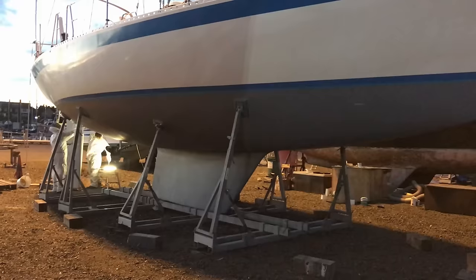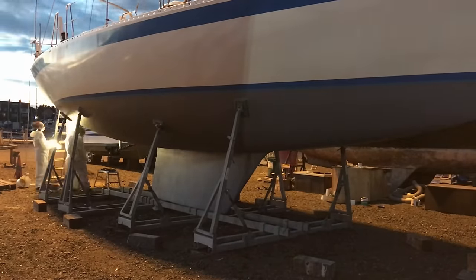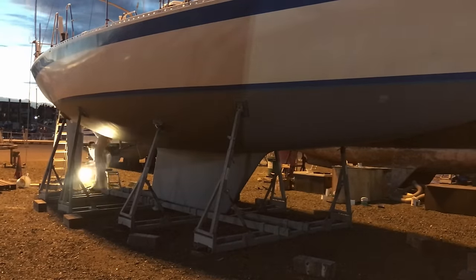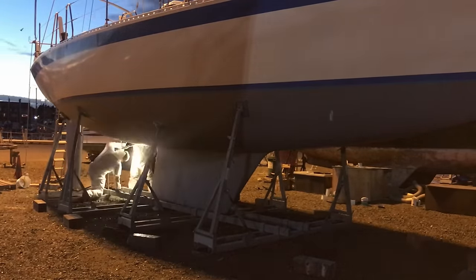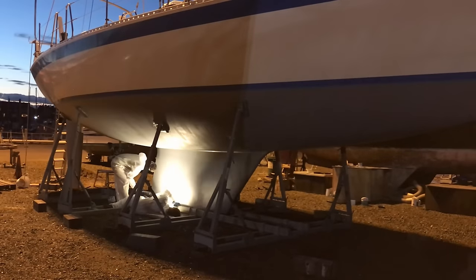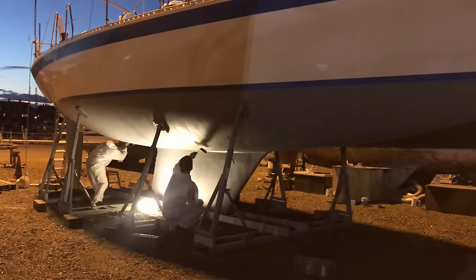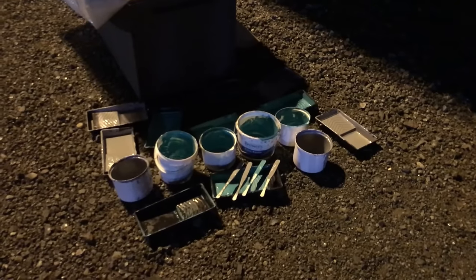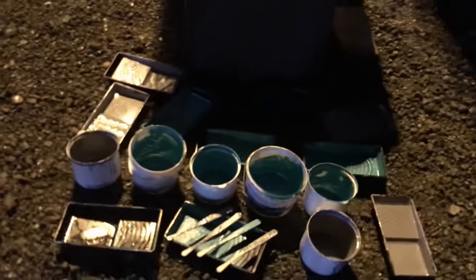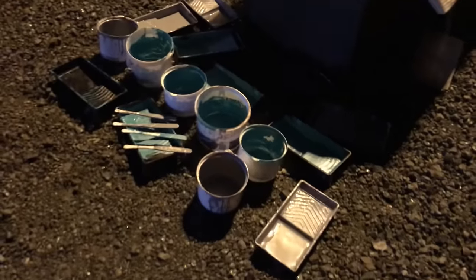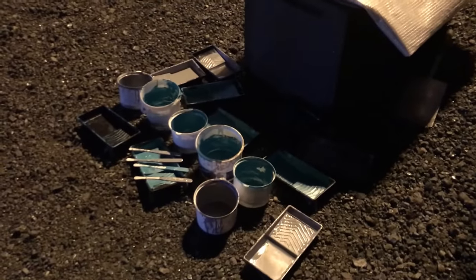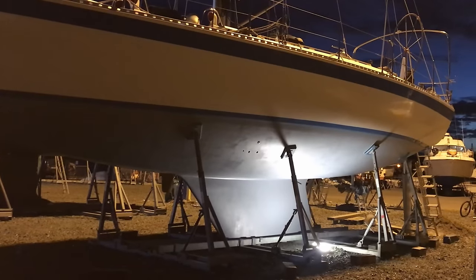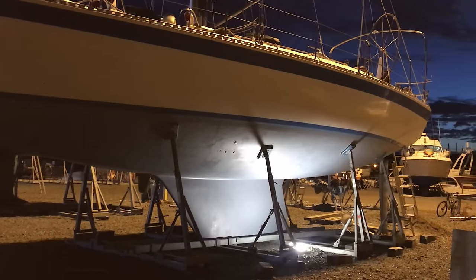One important thing to note here is, even though the barrier paint and the copper coat we're going to be applying are both technically epoxy based, they are fundamentally quite different, as the Coppercoat resin is actually a water-based product, and Coppercoat warned that any vapour from another type of coating that you're applying to will potentially react with the Coppercoat. So unfortunately, this means we have to wait 4 days for the barrier coat to fully cure before we can paint over it.